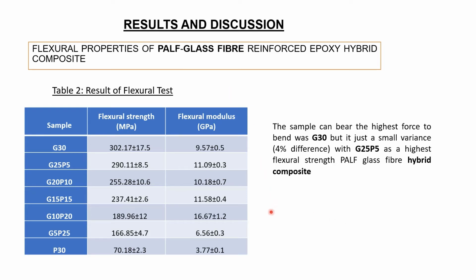Based on the table here, we can see that the highest flexural strength is G30 and the highest for hybrid composite was G25P5. Meanwhile, for flexural modulus, the highest one was G10P20. The sample that can bear the highest force to bend was G30, but it's just a small variance, a 4% difference with G25P5, the highest flexural strength glass fiber hybrid composite.